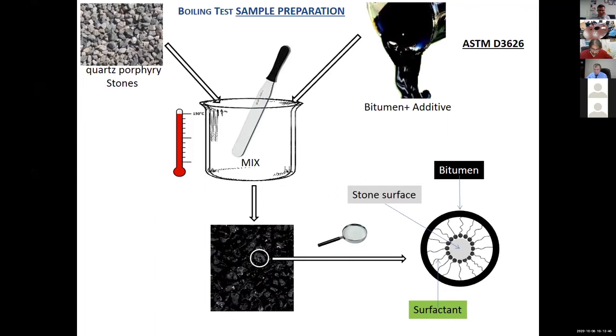Millimeter. The aggregate is a stone having acid chemical nature, quartz porphyry. The boiling test procedure used in this study was according to ASTM normative. In particular, the sample was placed in the boiling water for 10 minutes and then cooled to room temperature. The water decanted and the sample let dry on a paper towel for 1 day.